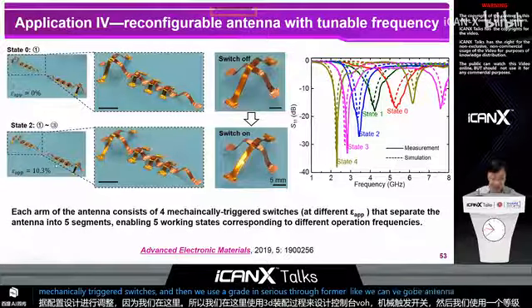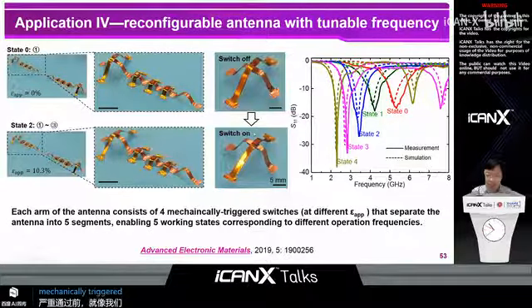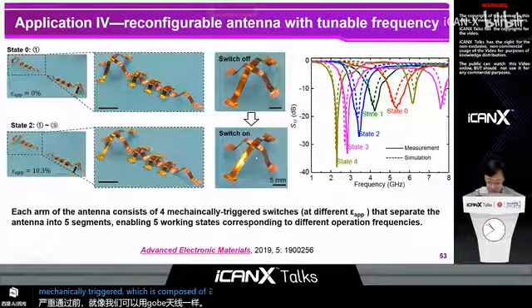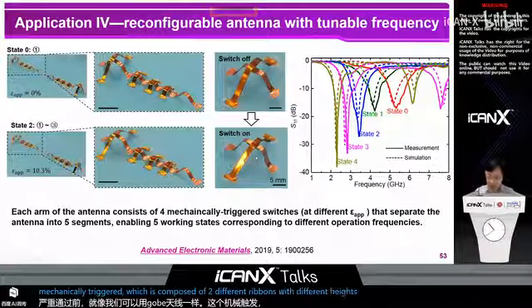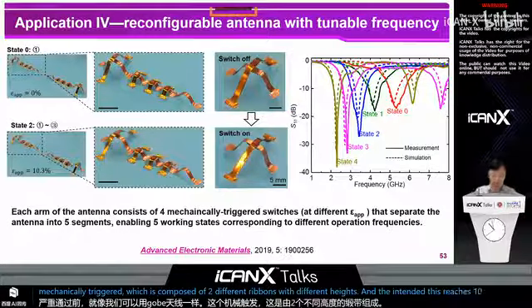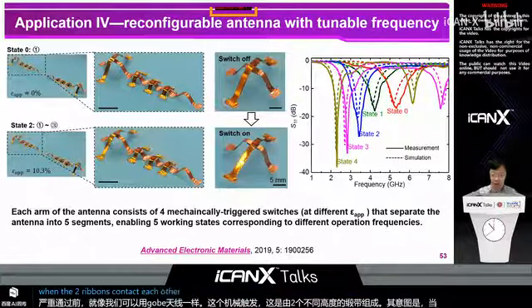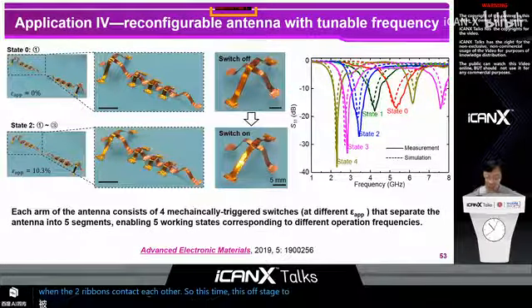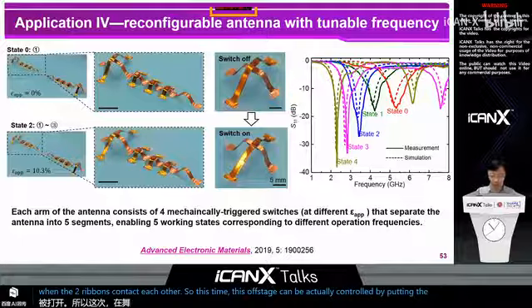This mechanically triggered switch is composed of 2 different ribbons with different heights. The switch is turned on when the 2 ribbons contact each other. So this on-off state can be actively controlled by pulling the substrate.